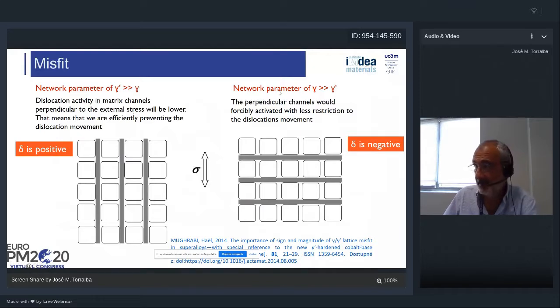And if this lattice misfit is negative, then the lattice parameter of the gamma is much higher than the gamma prime, and then the dislocation tends to move in the perpendicular channels in the gamma matrix. So that means we will have, in principle, worse mechanical properties.